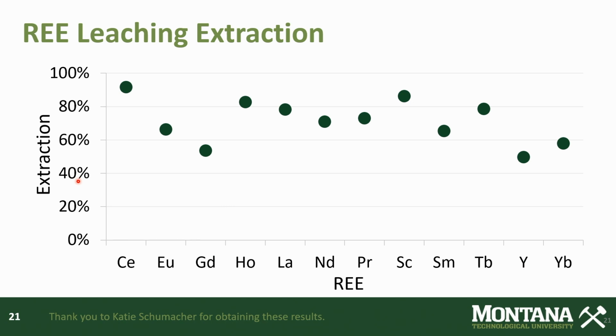One other thing I'll point out, if we're dealing with a concentrate, it's difficult, as some of you may appreciate, to effectively concentrate rare earth elements. So maybe you're going to get a 50% recovery through a physical concentration method. If that goes to conventional hydrometallurgy, you might recover 50% more of the rare earth elements. So the mathematicians in the crowd will understand that means we're wasting 75% of the rare earth elements that have been mined. So that's one of the things that we're trying to get away from here.